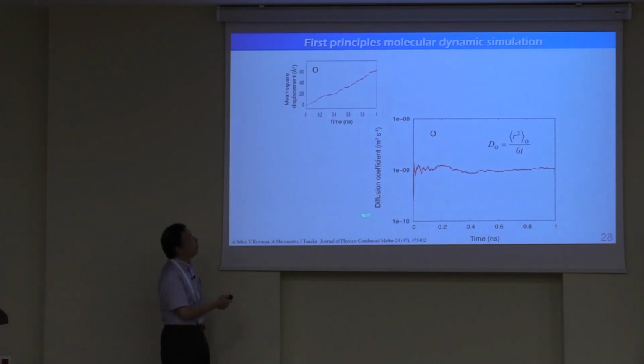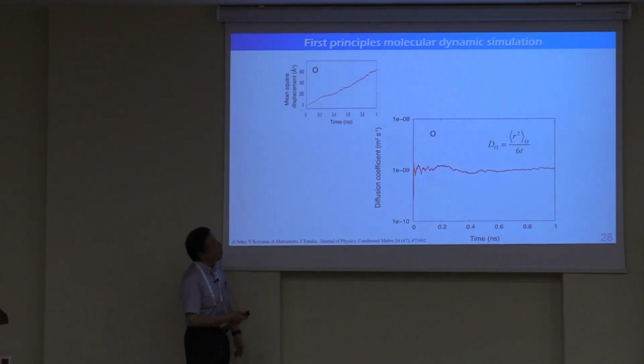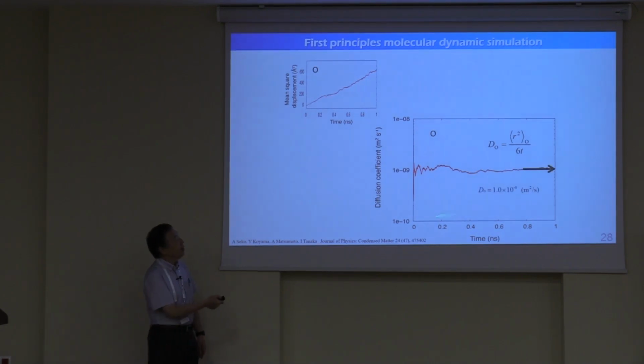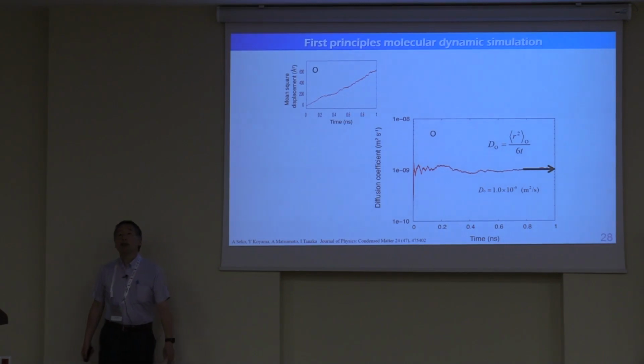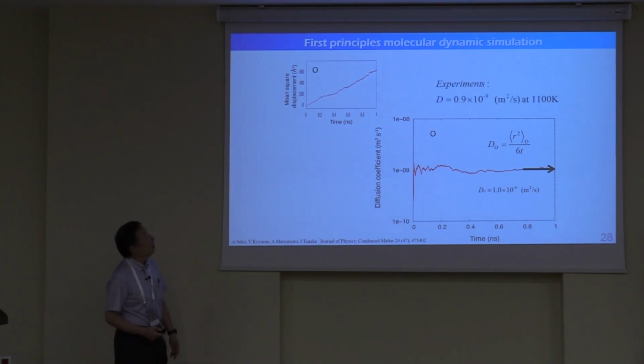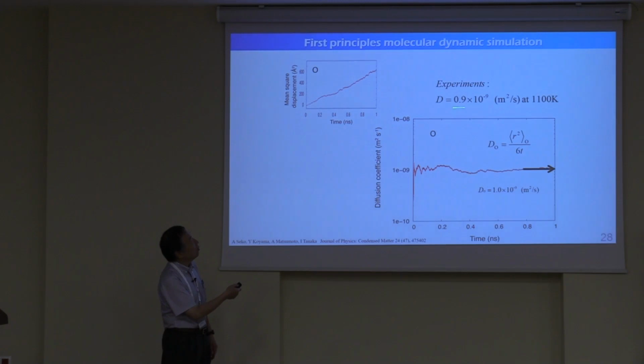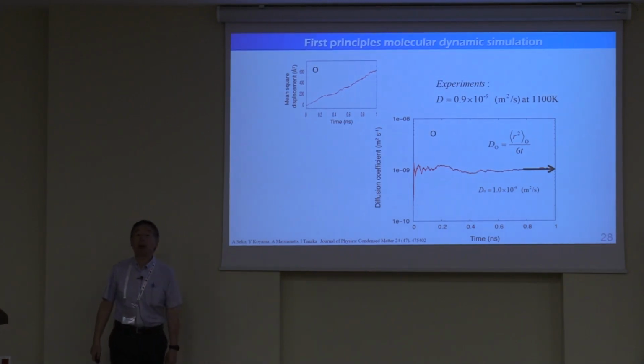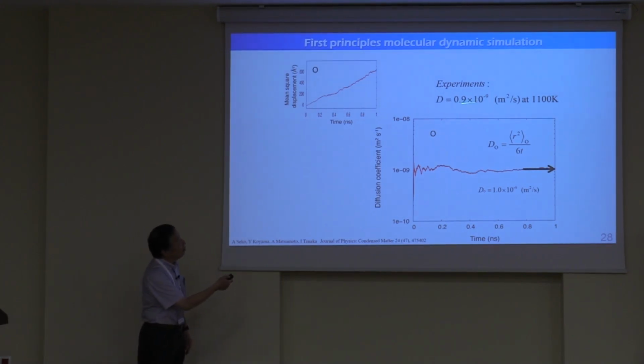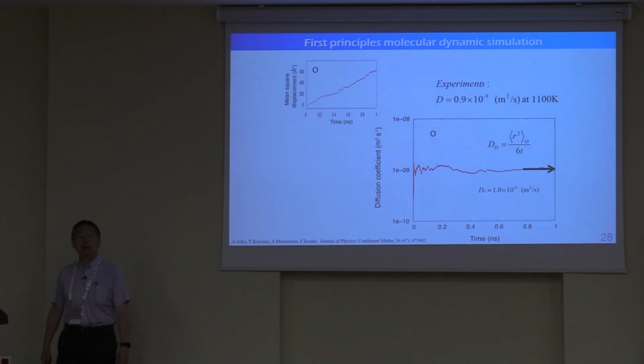So this is a diffusion equation for diffusivity with time. And it is almost converged at around 500 picoseconds, at a diffusivity of 1.8 times 10 to the minus 9 square meter per second. By experiment, it was 0.9 times 10 to the minus 9. So again, you can find that the agreement between the experiment and the theoretical calculation is quite nice.